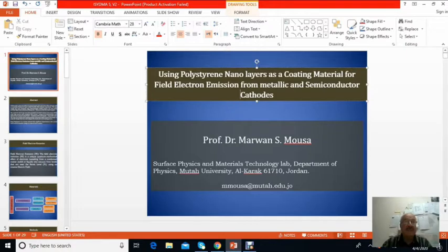Of course, their performance can be characterized in terms of beam brightness, emitter lifetime, short and long-term current stability, and previously we incorporated the energy spread measurements also. Several materials were used to coat the core material, the tungsten and the carbon fibers, such as several types of epoxy resin, hydrocarbons, alumina, lacquer, plastics, zinc oxide, magnesium oxide, zirconium carbide, and tetracyanoethylene, carbon black, etc.